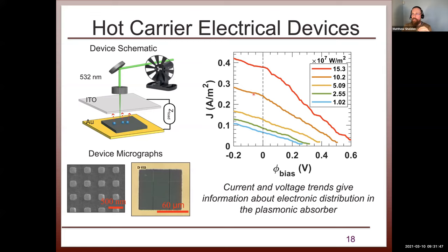these are just the hot electrons. These are the non-equilibrium, thermalized distribution of the hot electrons in our signal. It turns out we can actually analyze this very nicely in terms of a Richardson expression, or basically a thermal distribution of the electron gas, and it really nicely matches what we observe experimentally.